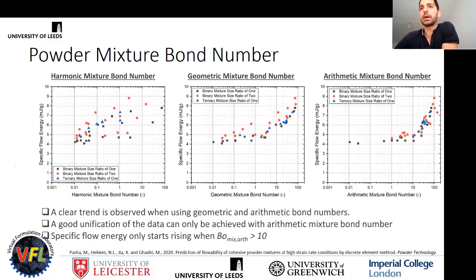We compared the 3 averaging techniques: arithmetic, geometric, and harmonic mean. And when we plotted these against the data we get from the FT4 rheometer, we managed to get a unification of the data for the specific flow energy, as we measure from the FT4, as a function of the arithmetic mixture bond number. So we can represent the cohesivity of the powder mixtures in terms of the arithmetic mixture bond number. So next was to come up with a rheological model. So if you move next, Csaba.